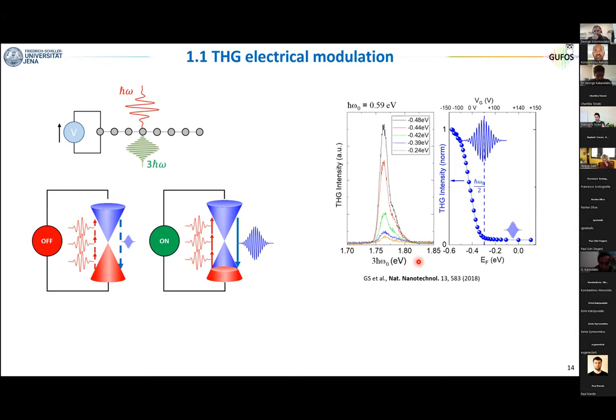So this trick of using resonances only works for atomically thin materials, so graphene and TMDs, because there the reabsorption is close to zero. So exploiting the resonances is, of course, one way of enhancing the nonlinearities, which is known also for bulk materials, but you cannot apply it to bulk materials, right? You can only apply it to TMDs or to 2D materials.